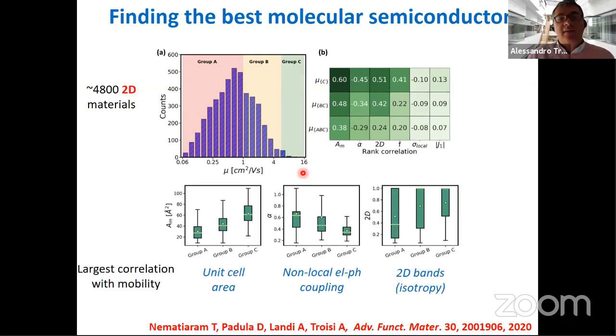And so what we discovered is that we consider the mobility as a function of all possible components that can affect the mobility. And we realized that the most important ingredient that makes the mobility high is actually quite trivial: the unit cell area. Because in a model where you have one orbital per molecule, if the molecules are more separated from each other, the mobility increases as the square of the area of the unit cell. Then the most important parameter before we did this work, which is still there, is the second most important: the non-local electron-phonon coupling, the fluctuation of the molecule, the thermal fluctuation. And the third one is what emerged from the map, which is essentially that you want a more isotropic band because 1D is very bad for transport.